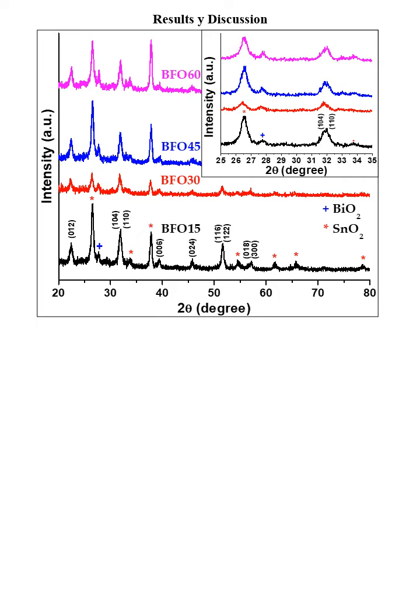XRD patterns showed that in all samples a perovskite type structure was obtained with a rhombohedral phase corresponding to the bismuth ferrite. And also it can be seen that in all samples a small secondary phase was obtained corresponding to the bismuth oxide. Also, it can be seen peaks corresponding to the substrate of FTO.